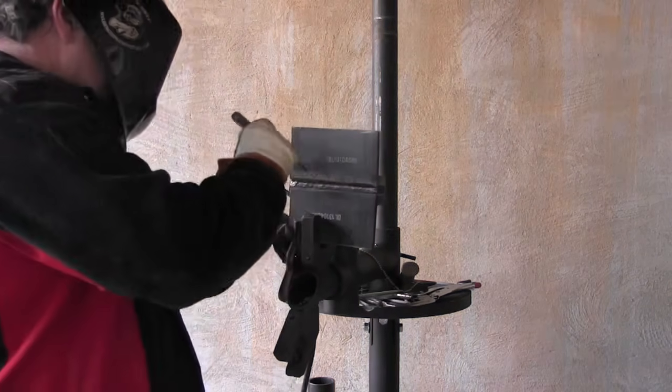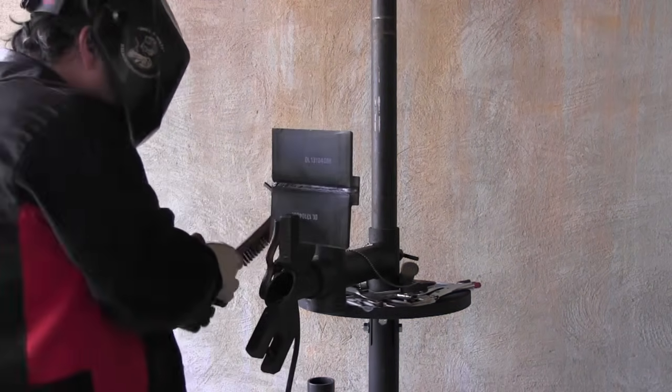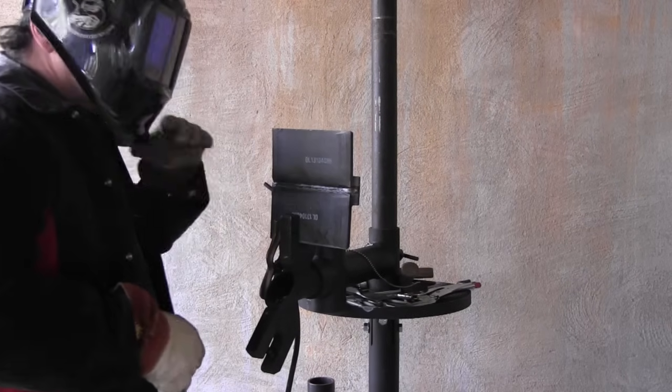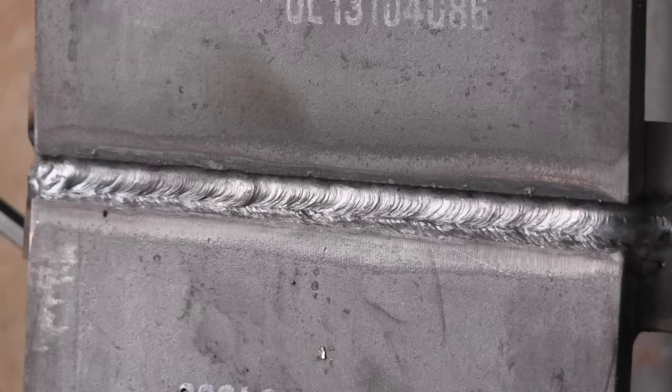That's where we stand now and I'll put the second one in there. I ran two or three of these plates. I'm going in a different direction on this pass than I showed just a second ago, but same thing applies. I'm trying to keep a good fairly tight arc length, go along nice and slow, watch the front of the puddle, making sure it looks like it is penetrating in and try not to leave any undercut. I'm in pretty good shape to run the last layer now. Just a little below flush toward the top.